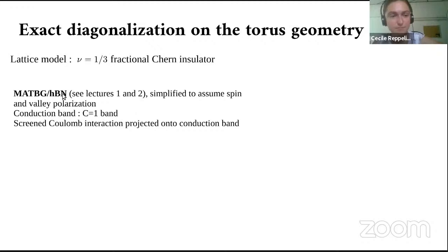Here I'm using the model from yesterday, the magic angle twisted bilayer graphene model with an added mass due to alignment with hexagonal boron nitride, which means I have a conduction band separated from the valence band by a gap. So I have a Chern band and I can project the Coulomb interaction onto the conduction band. For the purposes of pedagogy, I'm assuming spin and valley polarization, even though we know that might not be the case in the realistic system.